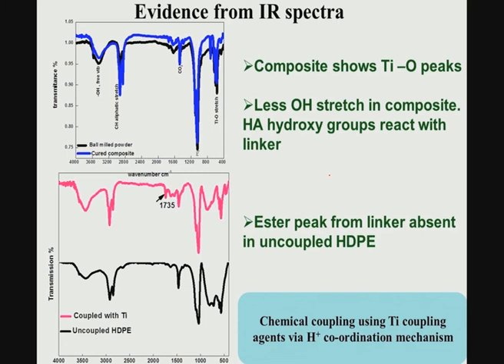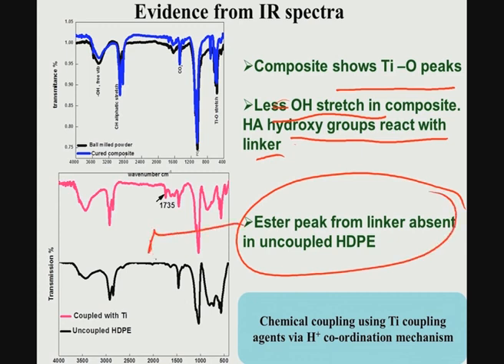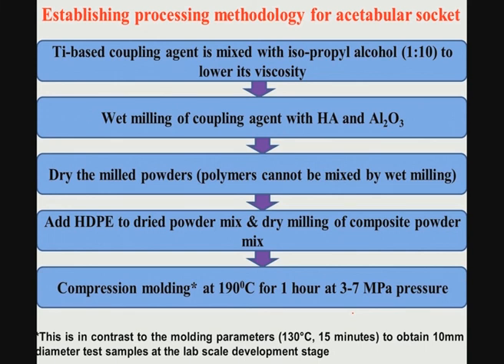Once you do this powder mixing and ball milling with the coupling agent and high density polyethylene, the spectrum shows some titanium and oxygen peak and a reduced stretch peak. That essentially shows that the hydroxyapatite or hydroxyl groups react with the linker. One can also notice an ester peak here, which is absent in the uncoupled HDPE. As far as the processing is concerned, one can use 2% or 3% of the coupling agent,